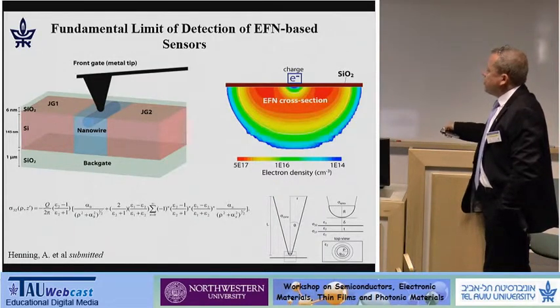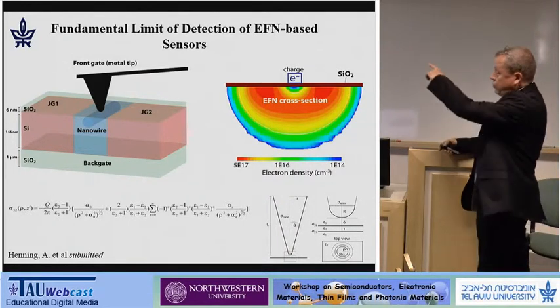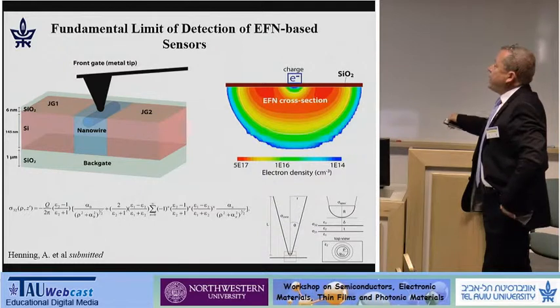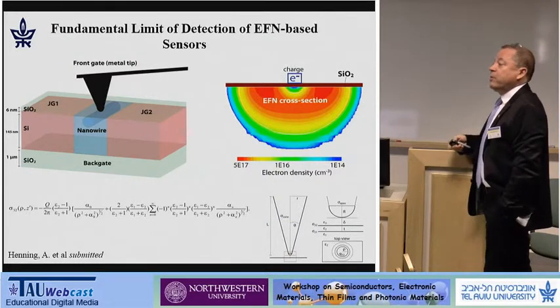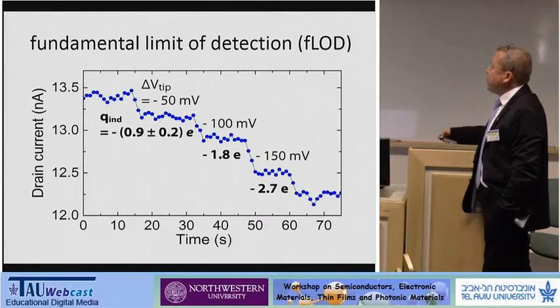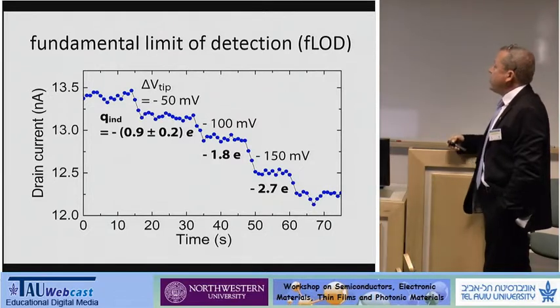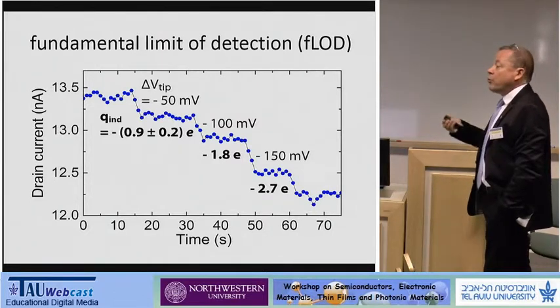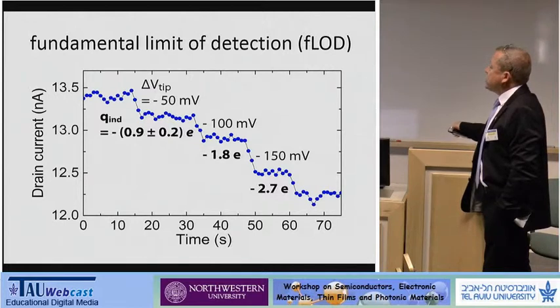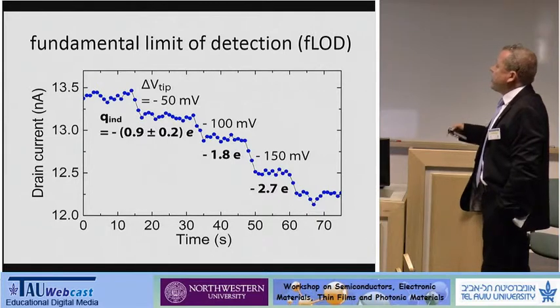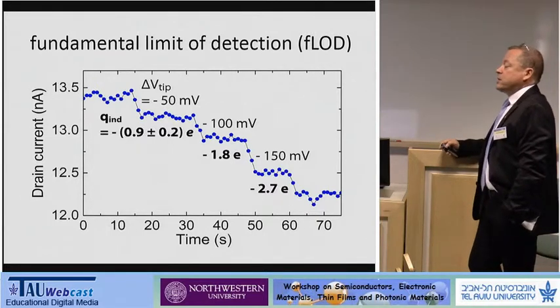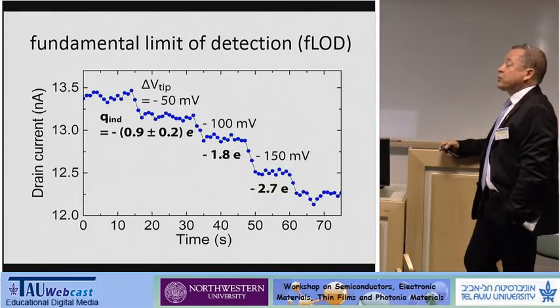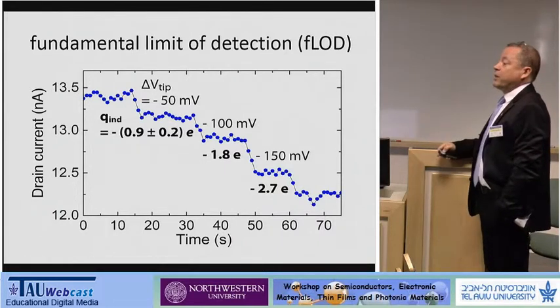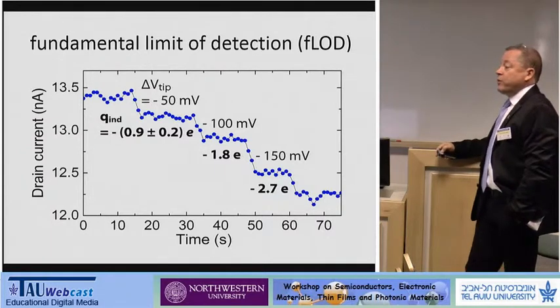Of this, you see, we apply source drain current vertical to the board through this nanowire and apply a tip gate bias and measure the change in the current. So each time we apply a step of 50 millivolts, we see a change in the current, which is above the noise. And by comparing this to a model, we came out with a sensitivity, which what we call limit of detection, or fundamental limit of detection. This device can be as sensitive up to less than a single charge, 0.9 of an elementary charge. So it can be a very, very sensitive device.